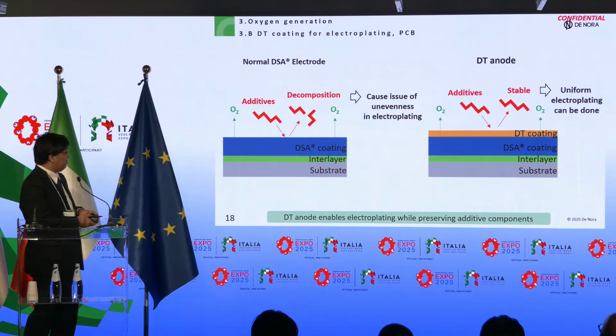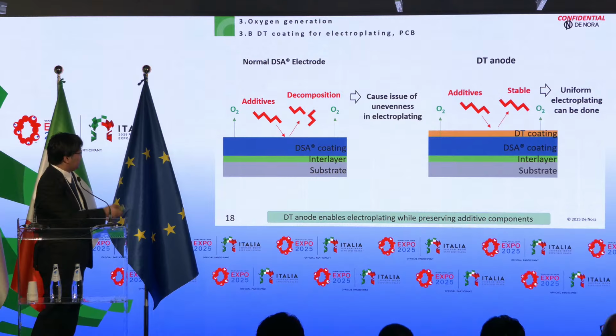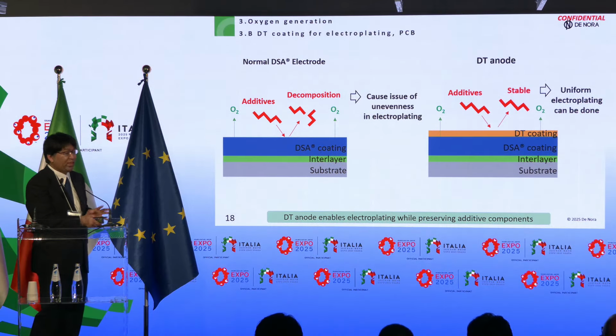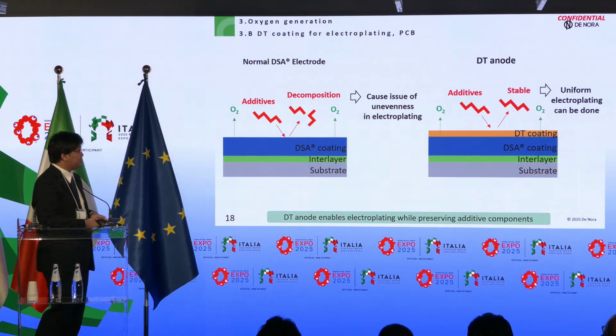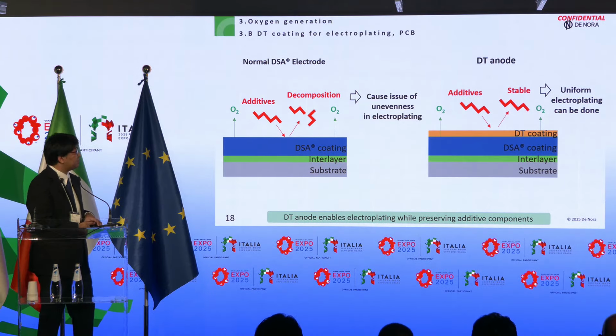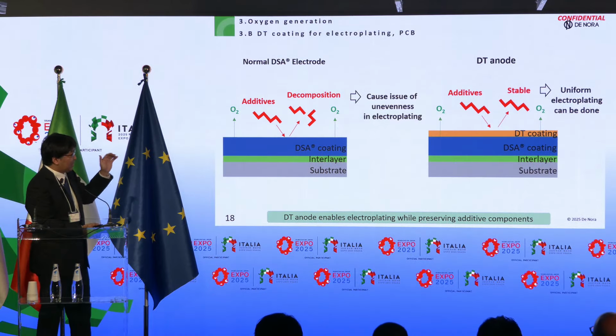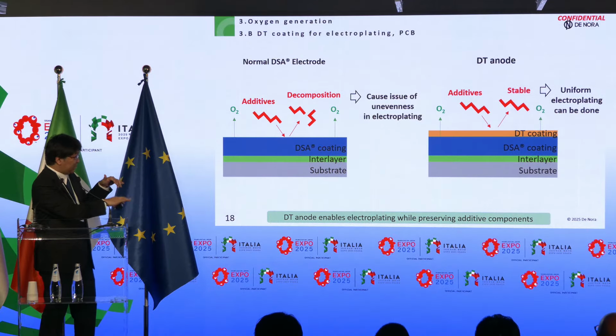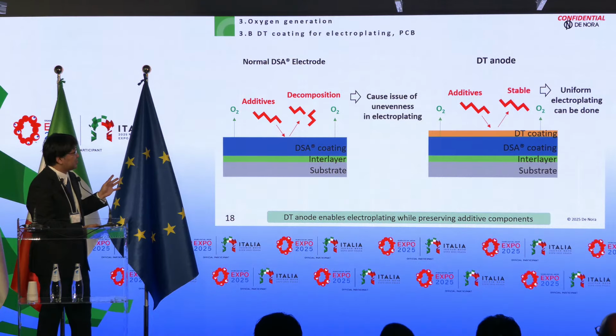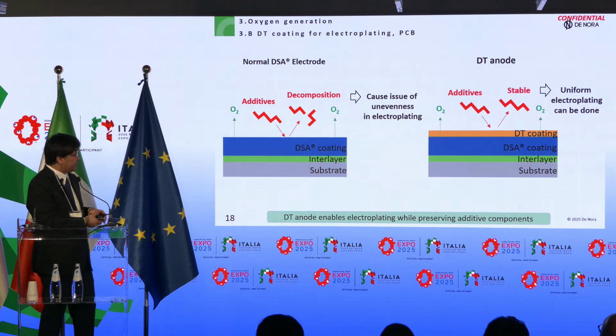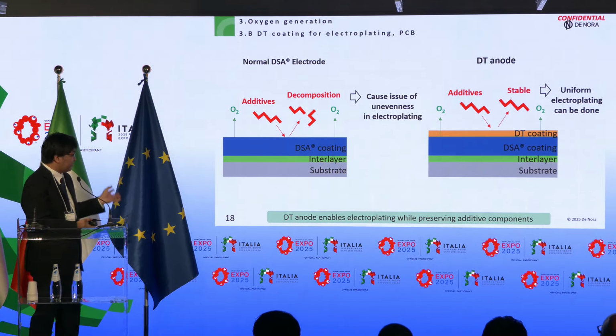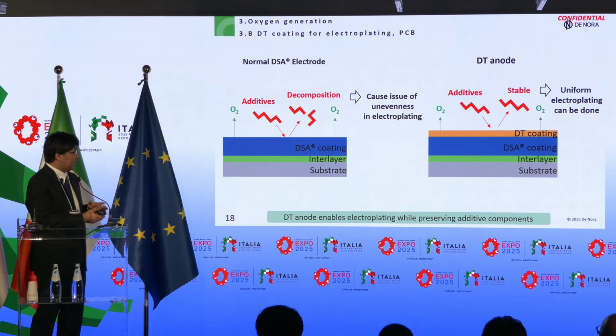And these additives can be decomposed by anode reaction in case of normal DSA electrode. And it causes the issue of unevenness in electroplating, decreasing the quality of electroplating films. So we developed the DT coating. DT coating is the top protective layer to prevent additives from reaching the active surface of the DSA coating. As a result, additives are not decomposed by anode reaction, and we can maintain the uniform electroplating film. So DT anode enables electroplating while preserving additives.